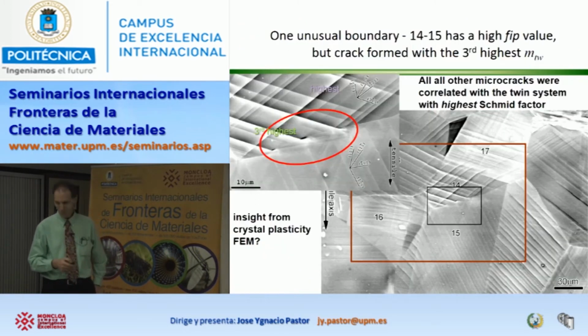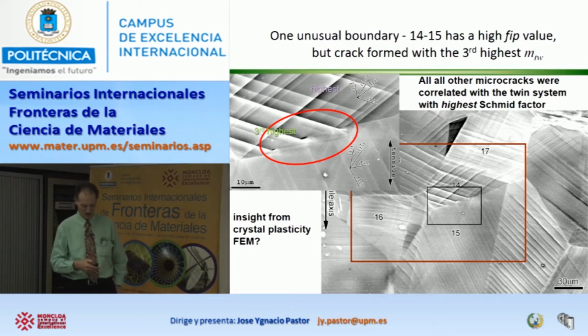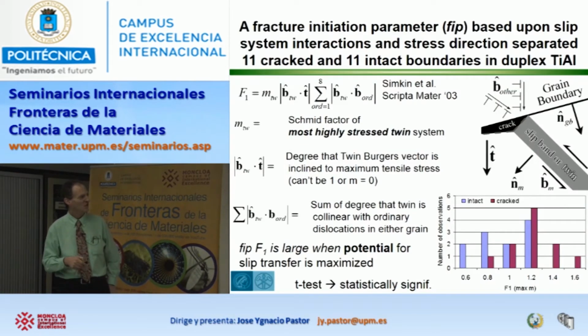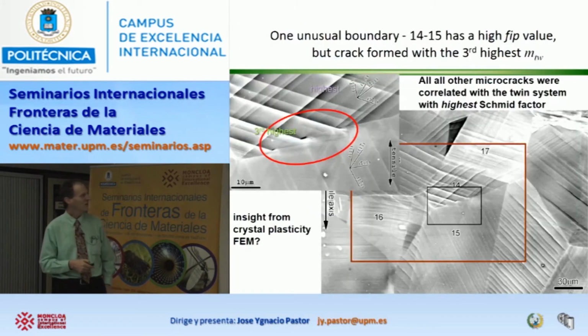So we had one boundary in the 11 that we looked at. I mentioned that first of all, it's difficult to get this information because it requires a tremendous amount of careful microscopy and orientation analysis to do this. So we basically found 11 cracked and 11 intact boundaries that we could compare. So here's one that didn't follow the rule. In this case, the twins that led to the microcrack here were the third highest Schmid factor twin system. The twins that had the highest Schmid factor did not cause cracks.